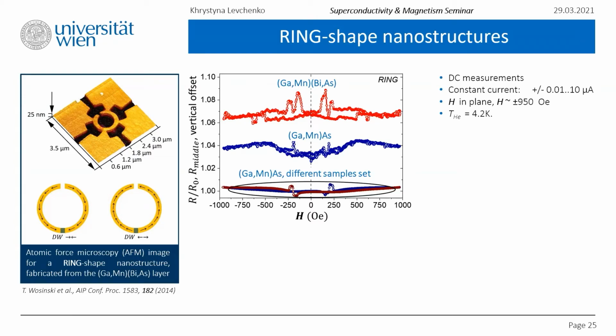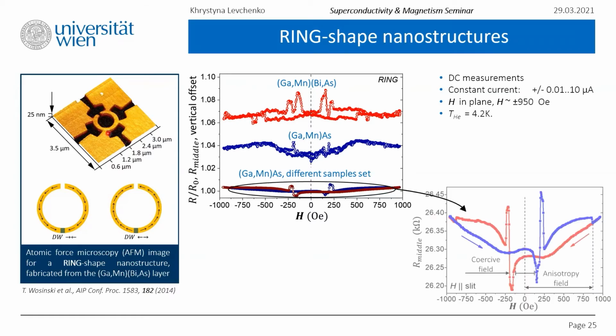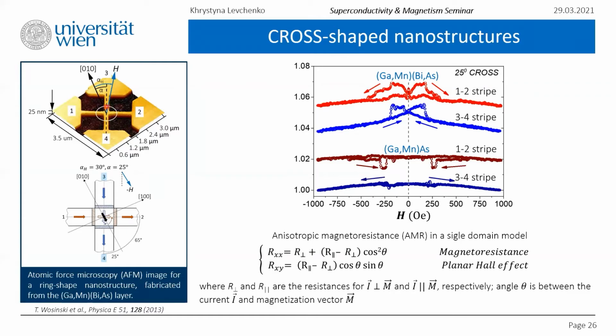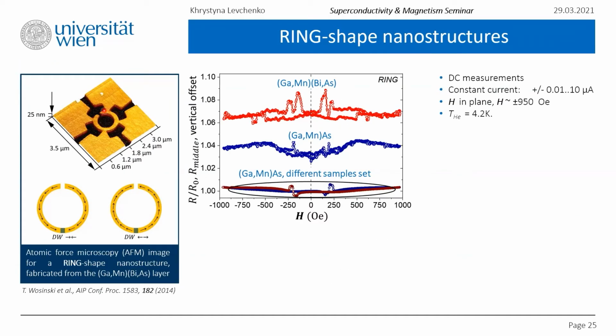So if one fabricates a ring segment, with the middle segment narrow enough, or for example, a cross stripe narrow enough, less than 100 nanometers, then this will tend to align the spin magnetic moments along the stripe or the ring segment. And this is caused by the misfit strain relaxation perpendicular to the stripe or the ring axis. So basically, we will have the spin alignment either in the configuration head to head or tail to tail. These are 2 domains in the case of nanoring and the domain wall separating them. We are manipulating the domain wall by applying a sweeping magnetic field.